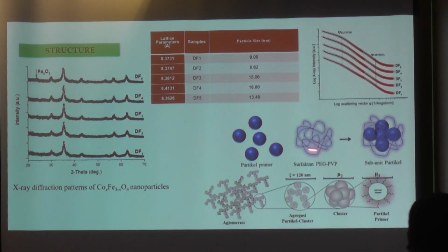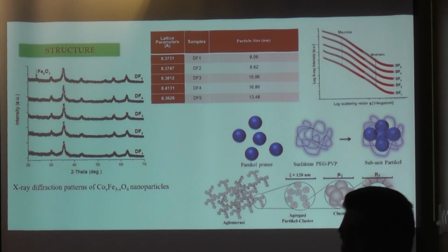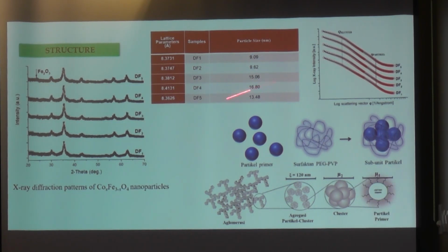So when ferrofluid is covered by PEG, a polymer, this is the magnetic fluid, the primary particle, and this is the polymer, and the composite, something like this. With the data we make a simulation, like a chain for the ferrofluid, and make a particle cluster, the bigger one, something like this, and in here covered by surfactant. If we measure using TEM or other techniques, it is impossible to obtain this data.